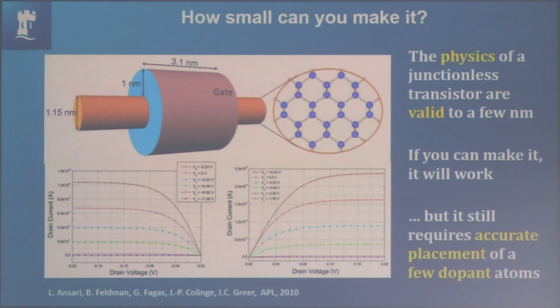The other thing is, what happens when you make things very small is you get quantum confinement and your band gap grows. So the dopant level, the impurity level, was no longer close to the conduction band, and could not thermally ionize. But the dopants were in there at such a concentration that they formed what we call a Mott conduction band.